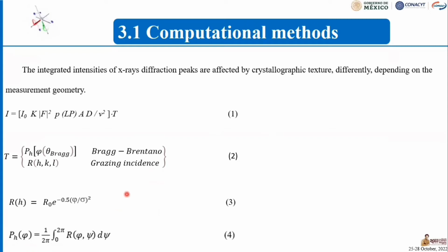So we have this model here, where phi denotes the polar angle measured from the location of the IPF, and sigma is the standard deviation of the orientation distribution, where R0 is the normalization constant such that the integral over the whole unit sphere has a value of 4 pi. Here is the calculation of the pole figure from the symmetry axis. The inverse pole figure proceeds by the application of the fundamental equation of the fiber texture.